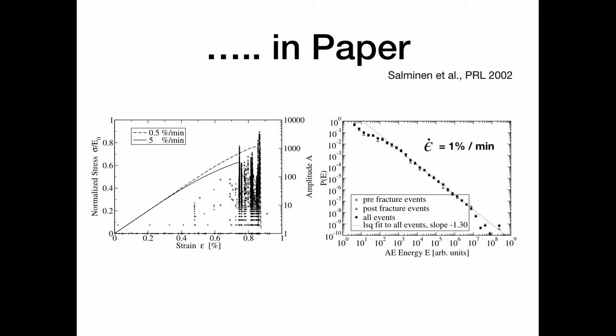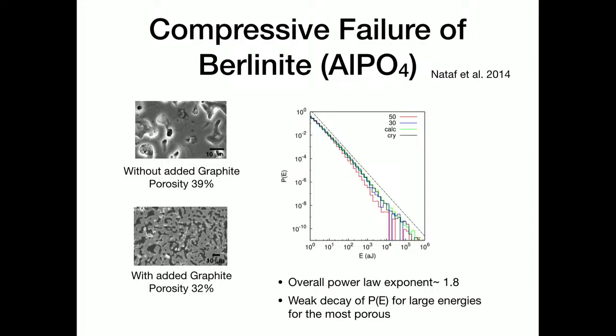At a lower rate, most of the activity occurs prior to the peak load. And what is shown here is an intermediate straining rate in which there is activity before this peak load as well as post that. And what is found is that the power law is fairly robust. Here it is the energy distribution. Earlier what was shown was the amplitude distribution, but they are connected, so you see the power law behavior in either of the distributions, or you can characterize either of them.